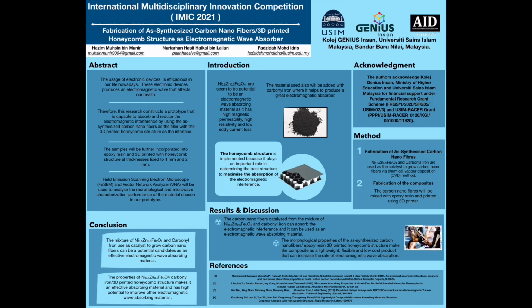The second phase is the fabrication of the composites. The synthesized carbon nanofibers will be poured into an epoxy resin base. The epoxy resin base composite will be printed at thicknesses fixed to 1 mm and 2 mm using a 3D printer in the form of honeycomb structure.